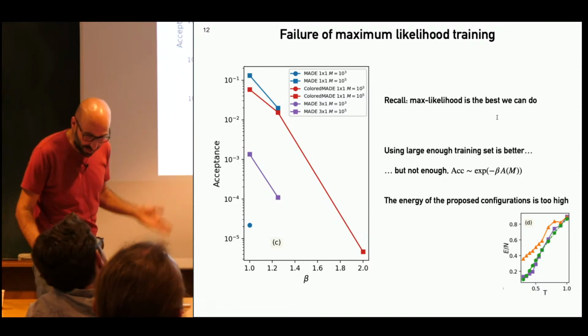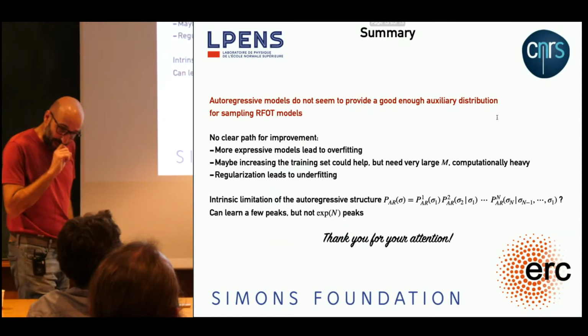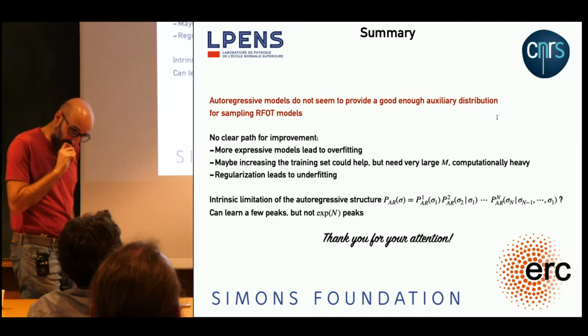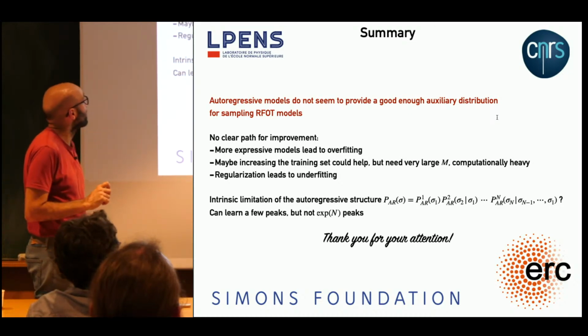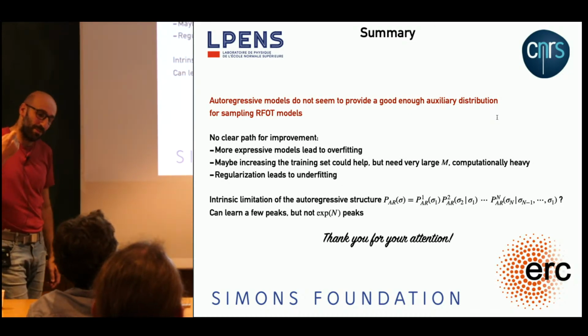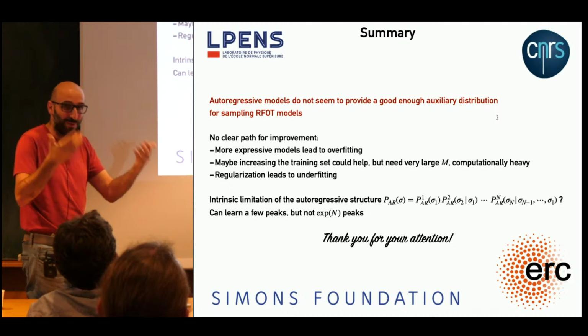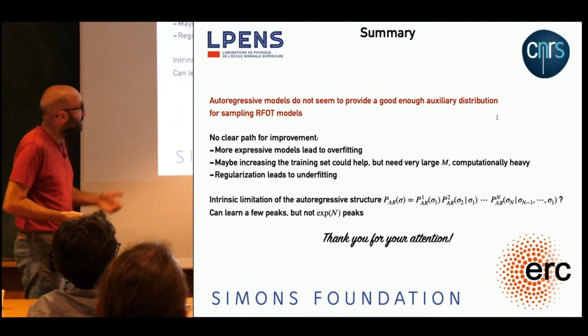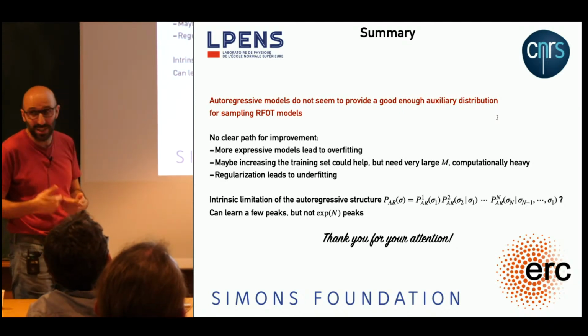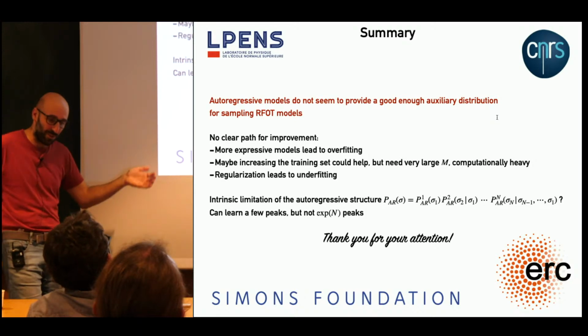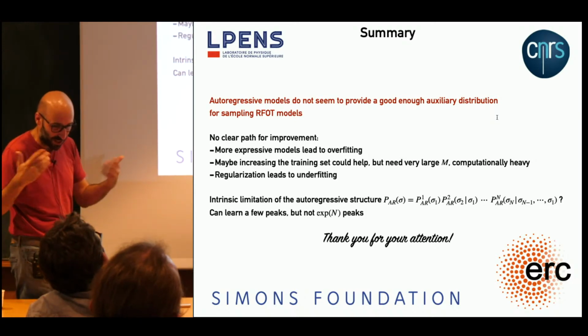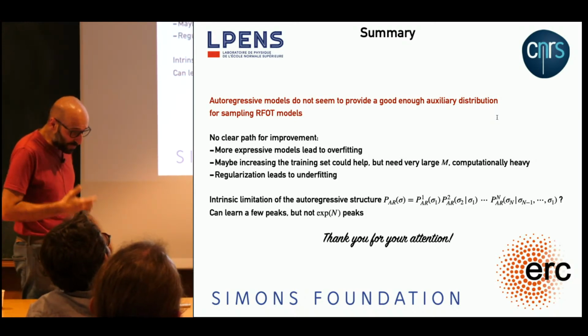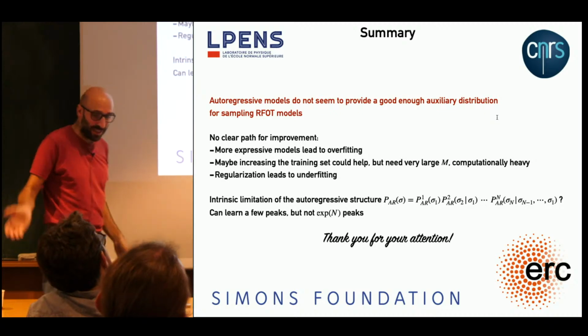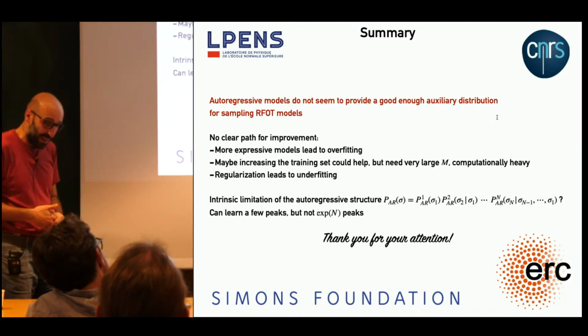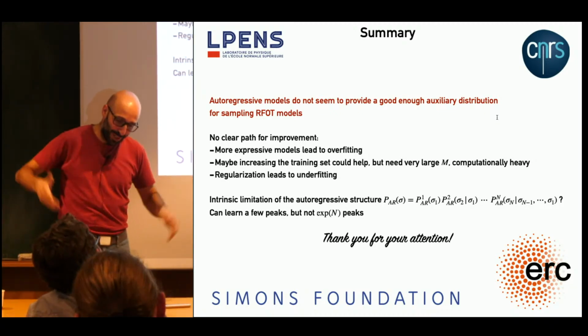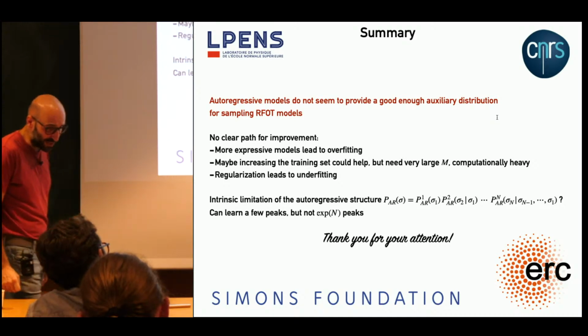So the conclusion is it doesn't work, and we didn't find a clear way to move forward. If you try to use a more expressive model, you get overfitting, and then maybe you have to increase your training set, maybe exponentially in temperature. If you try to put some regularization, then you increase the entropy too much and you go into the underfitting.